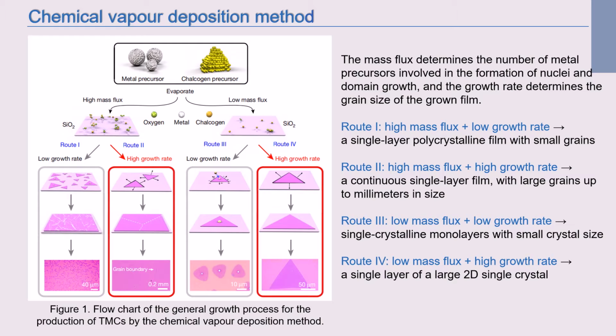Figure 1 shows the general growth process for the production of TMCs by the chemical vapor deposition method, which is based on the competition between mass flux of the metal precursors and the growth rate of the domain. The mass flux determines the number of metal precursors involved in the formation of nuclei and domain growth, while the growth rate determines the grain size of the growing domain. There are usually four possible routes in this process, as shown in the page.